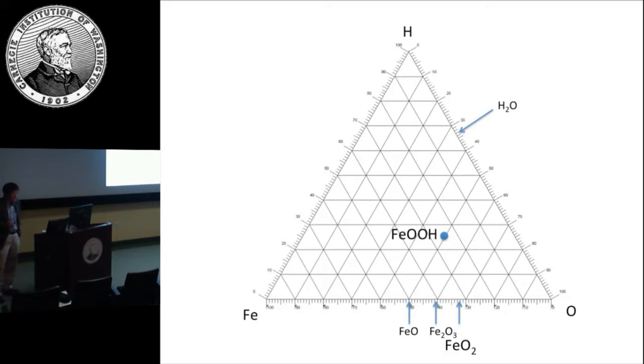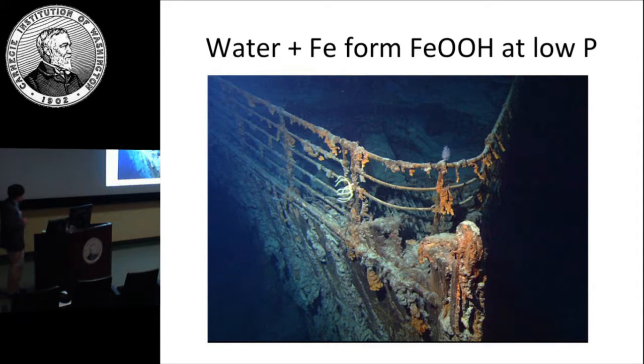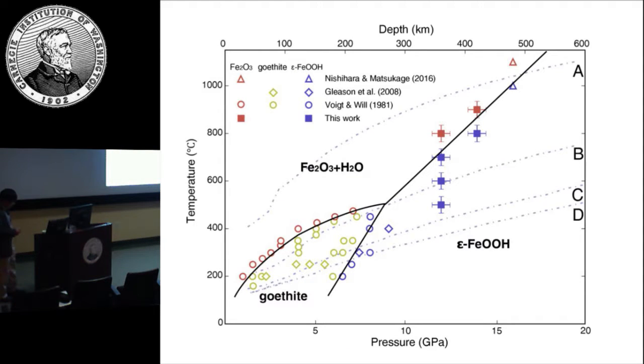Okay, so then we say, maybe you can extract some oxygen out of the water. So if we start with Fe2O3 and put water there, and you can take the water out of here, then you can make this thing. At ambient conditions, it works the other way around, because this is more stable than the end member. But at high pressure, maybe this will change. So we tried another experiment. At low pressure, if you put water and iron together, it forms FeOOH, called goethite, and at high pressure it forms an epsilon phase. It's a distortion of the goethite phase.